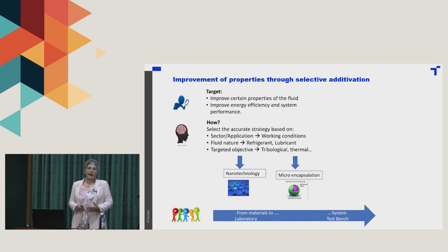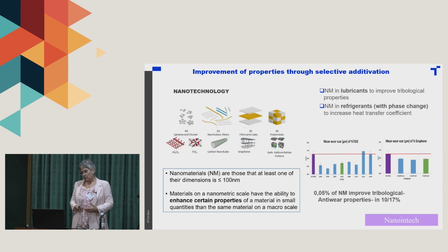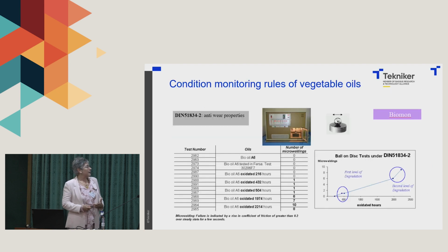And also to highlight that it's possible to improve the additivation of the lubricant using nanotechnology, can be nanoparticles or graphene, or also by microencapsulation in order to control the temperature during time. But it is possible to see that only with a very small quantity of nanoparticles it is possible to reach a substantial reduction of the wear scar. But one thing that is important is to control oxidation, as we have highlighted.